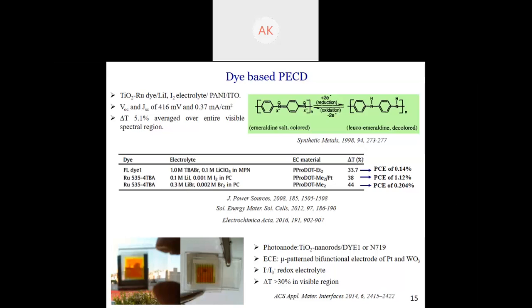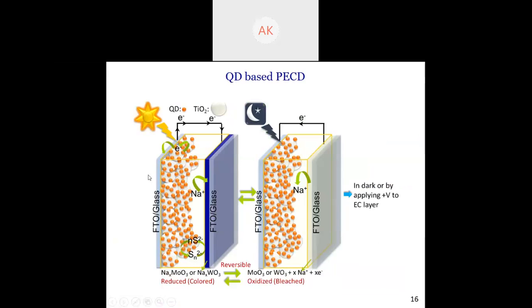So here we come to quantum dot sensitized PECDs. The working principle of a quantum dot based PECD is very similar to a dye based PECD. Upon photoexcitation at the anode side, electrons get generated and move to the FTO glass, from which they flow through the external circuit to reach the counter electrode. At the counter electrode, we have the electrochromic material, WO3, coated over it. When this electron gets inserted into the lattice of the WO3, Na+ ions, or the cations from the electrolyte, also get inserted simultaneously. So it gets reduced to form NaxWO3 as the case may be,